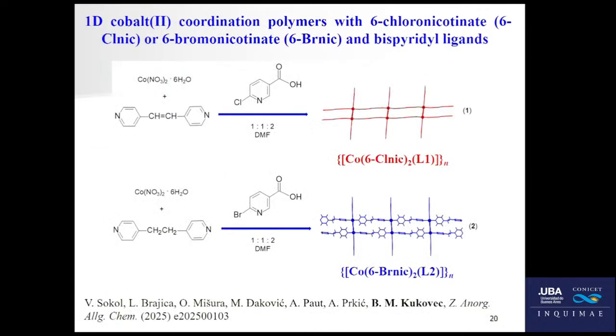After that, we did some more studies, but this time we wanted to exclude water as a solvent, so we used exclusively DMF. Okay, DMF maybe contained some water, but it was not distilled, not dried. So we used again the cobalt salt, but instead of the previous bipyridine we used the bipyridine ligand that I mentioned on one of those previous slides.